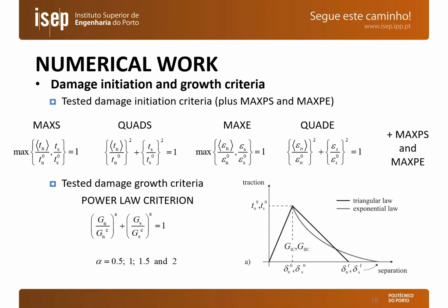We can see in this slide the different damage initiation and damage growth criteria used for the XFEM. Beginning with damage initiation, we considered 6 criteria: the maximum stress criteria, max S, the quadratic stress criteria, quad S, the maximum strain criteria, maxE, the quadratic strain criteria, quadE, and also the max PS and max PE criteria, which are based respectively on the principal stresses or principal strains.